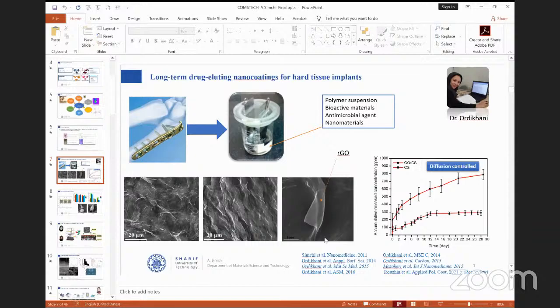We had in mind, with Professor Boccaccini at Imperial College, to create a thin layer on the surface of titanium by a polymer material which contains bioactive materials, antimicrobial agents, and also nanomaterials. Therefore, what we did is to use electrophoretic deposition, as you see in the SEM pictures and images.